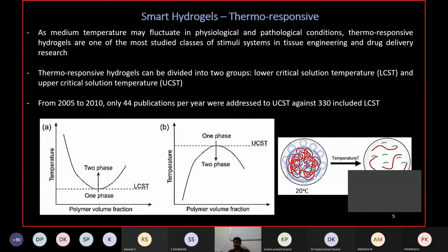The temperature, you cannot state it randomly. You should mention the lower critical solution temperature and upper critical solution temperature, because otherwise it would be difficult to describe them. And these properties are so essential to know whether they are mixing with the solvent. See, lower critical solution temperature refers to the conversion of two phases into one phase, below which the phase is 1 and above which the phase is 2.